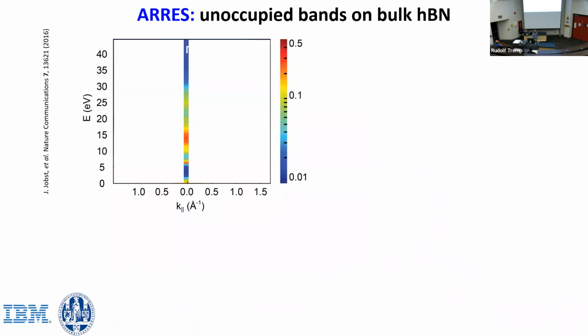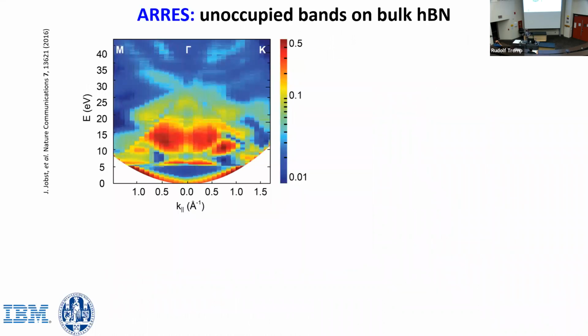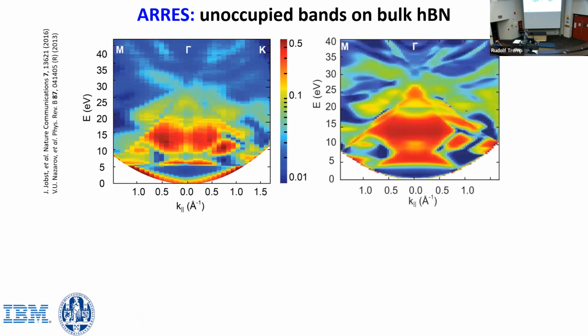So here's the same thing on boron nitride. You see a very different pattern. Here's a first principle simulation. We see a strongly occupied state here. Blue means low reflectivity. We see that in the experiment. A big band gap in the middle here, which you see in the experiment also. You see these side bands here and here that occur in the experiment.